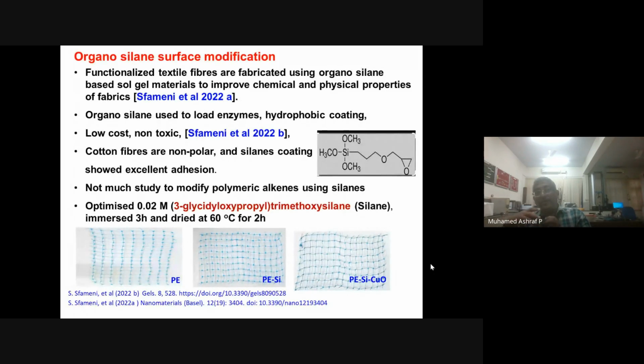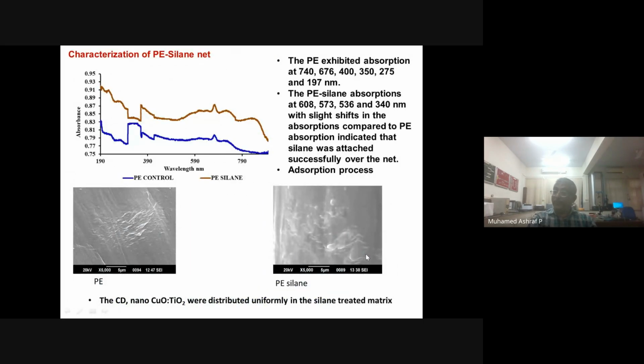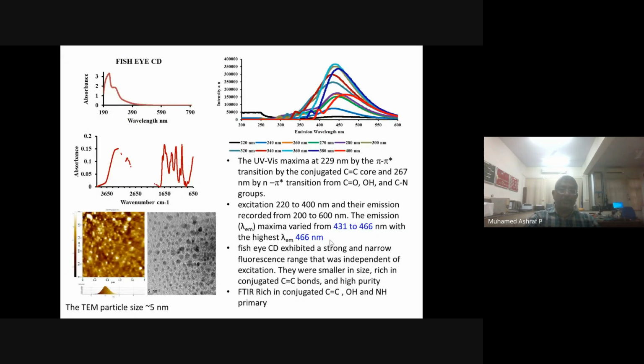So we devised a methodology using 3-glycidyloxypropyl trimethoxysilane. This I generally call silane, and we found that it is very good. It is very successfully attached over the aquaculture cage net, and over that we have added copper oxide also. And these are all the characterizations used, SEM and all. We found that this was a very good attachment.